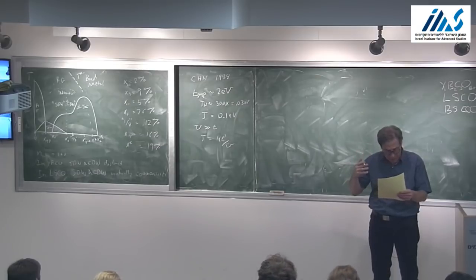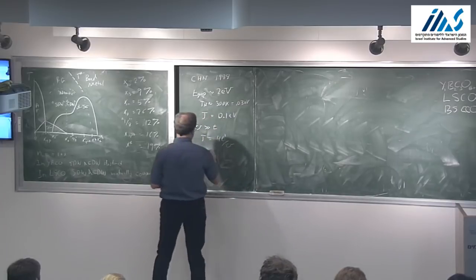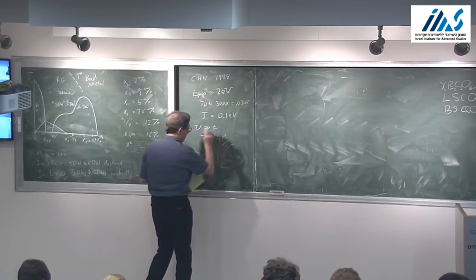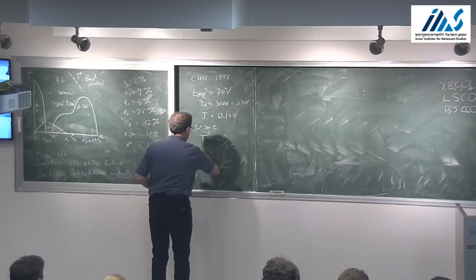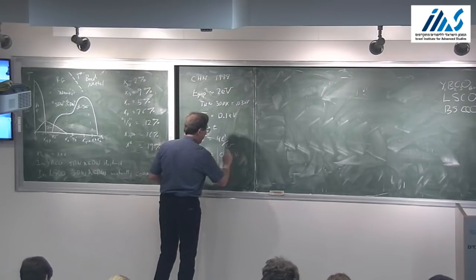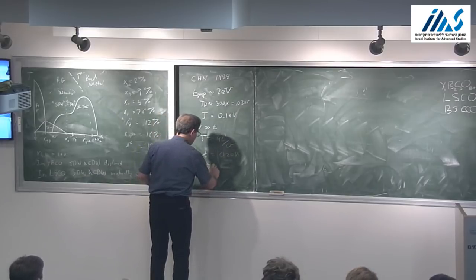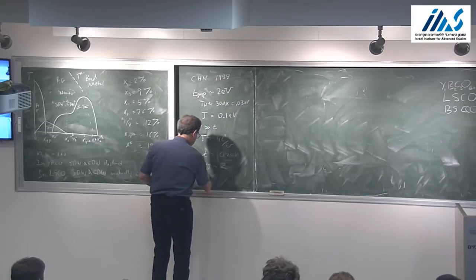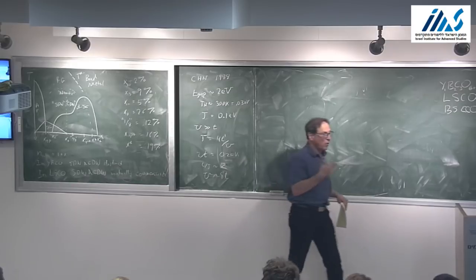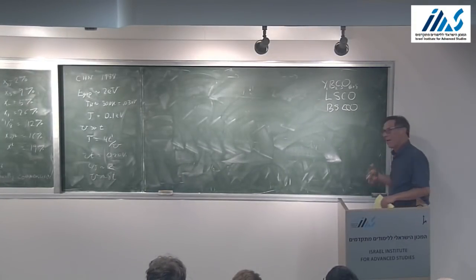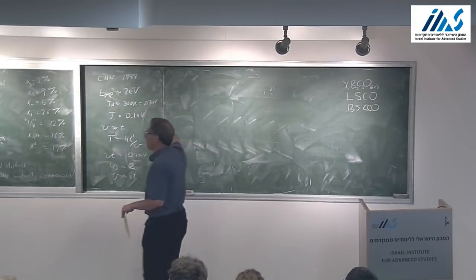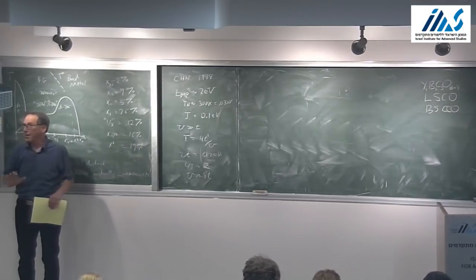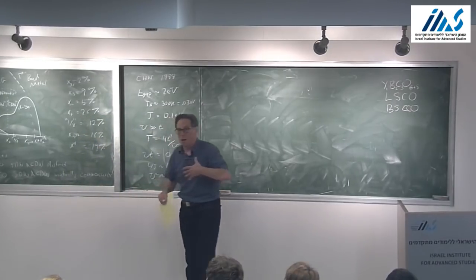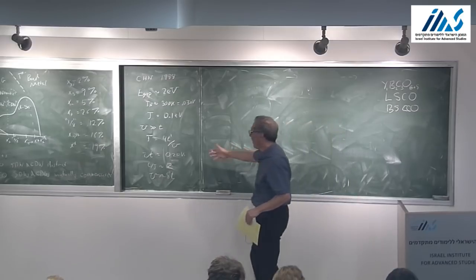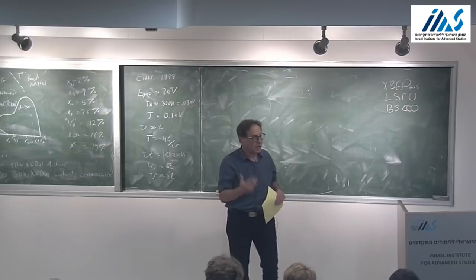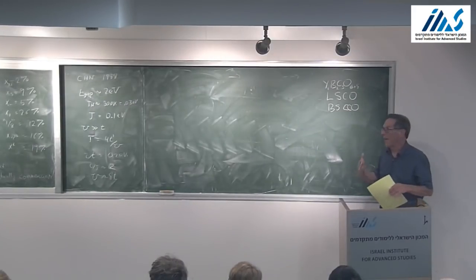Now, if you think about this too microscopically, there is actually a slight problem with this. If J is a tenth, it turns out the characteristic hopping is something like 2/10 of an eV. And so it means that t over J is something like 2, which means that U is something like the bandwidth. So really, if you track back, you would conclude that the actual problem is an intermediate coupling problem. But in order to understand the magnetism, whatever the microscopic values of parameters, the right way to think about it is from the strong coupling perspective, where the gap simply has to do with the fact that you can't move charge around without putting 2 electrons on a site. It's a pseudogap in the sense that it's a gap that's not directly associated with the development of any broken symmetry.